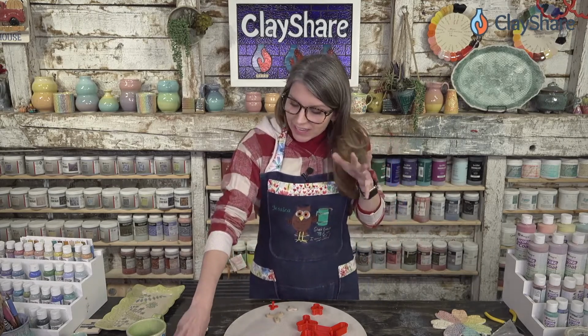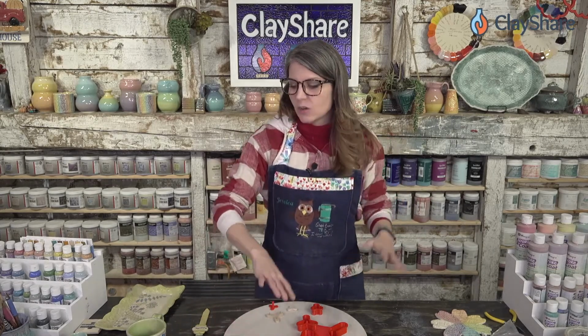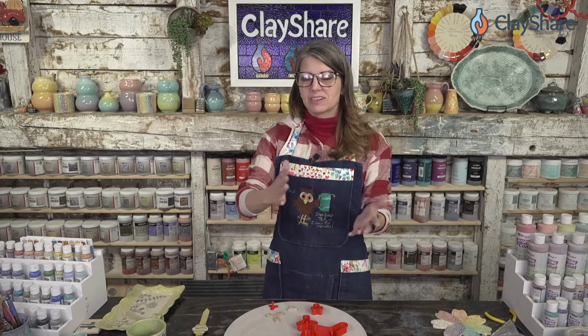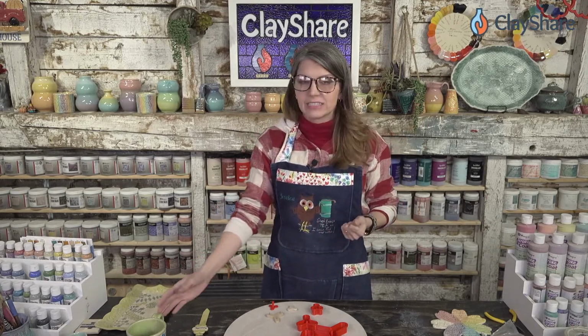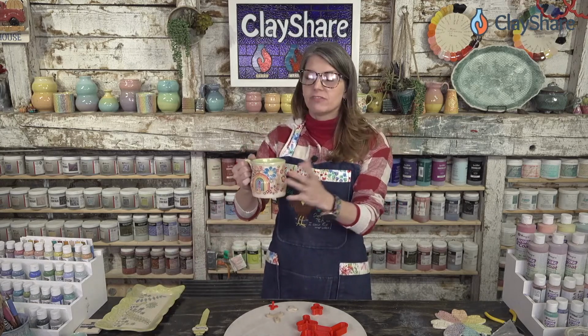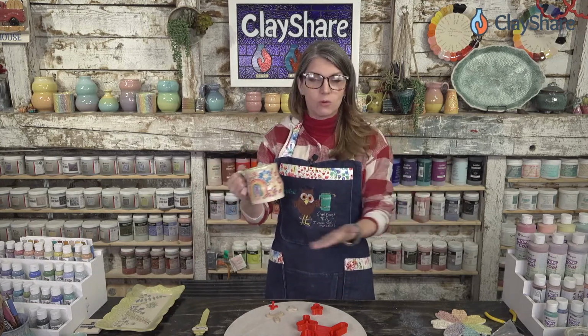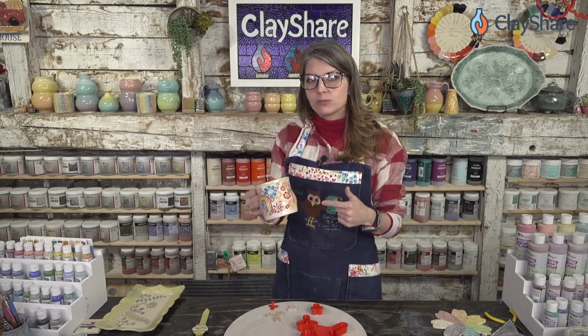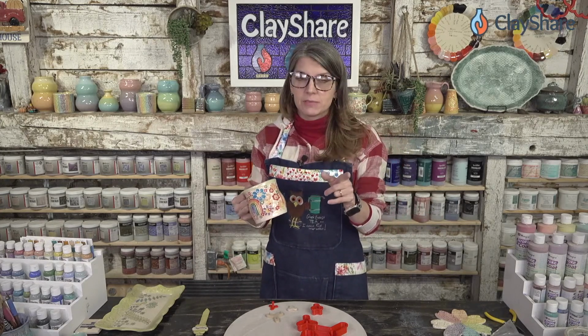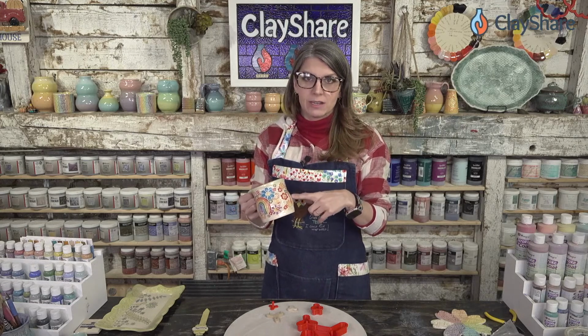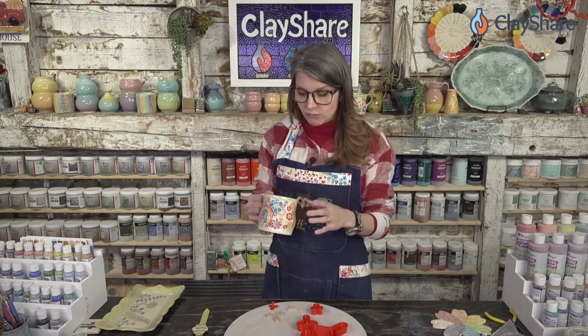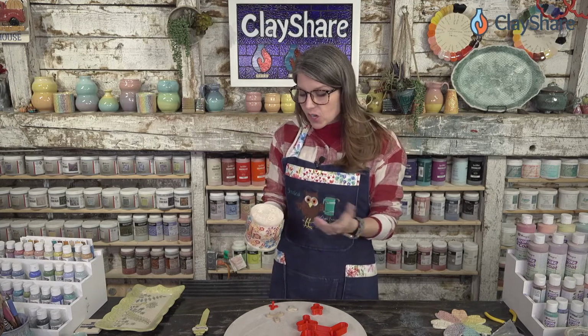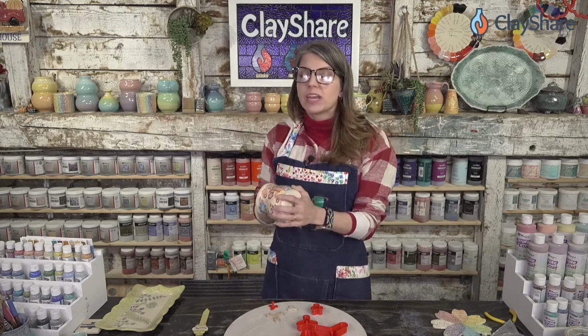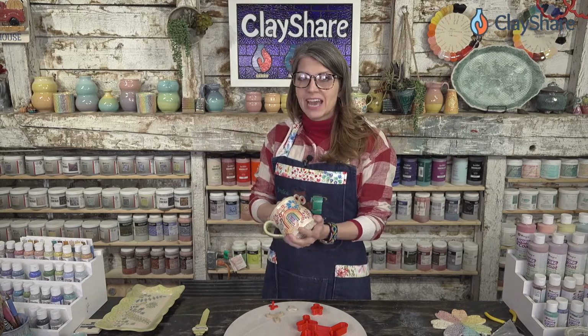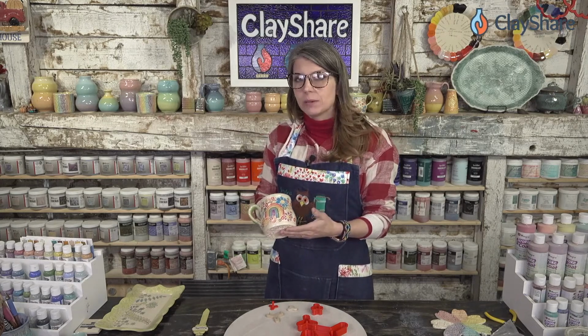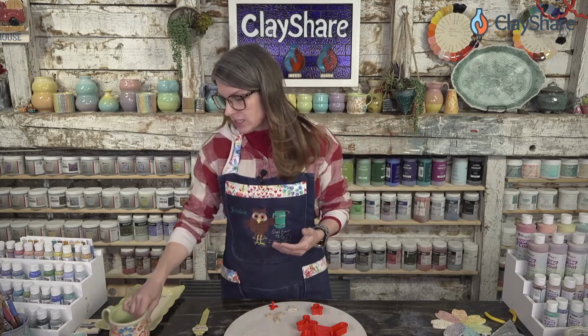And you have to find that point between when the clay is vitrified and when the clay slumps. And manufacturers give us guidelines, like Laguna says their B-Mix 5 fires to cone 5. So we know, fire it to cone 5. Can you take it to cone 6? Yes. Although sometimes if you go to cone 6, you could get bloating and you might get some slumping. So you've got to watch out for those things. Can you fire it cooler than cone 5, like a cone 4? You can. It won't be as vitrified, so it might weep a bit. So just keep that in mind if you're not going to take it to its top temperature.